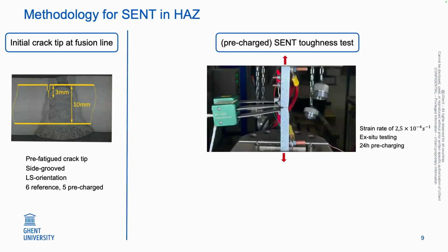First, the specimen: a 10 by 10 cross section single edge notch tensile specimen with a length of 100 millimeters. We try to position the pre-fatigue crack tip in the heat affected zone as close as possible to the weld. So we try to position it in the coarse grain heat affected zone at a depth of 3 millimeters, according to the standards. And then our test itself, we test after 24 hours of pre-charging.